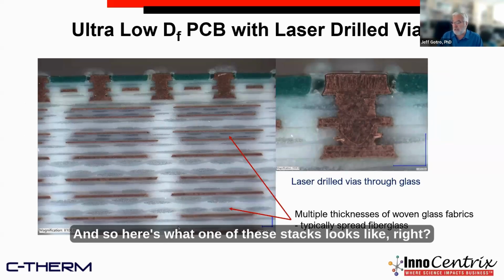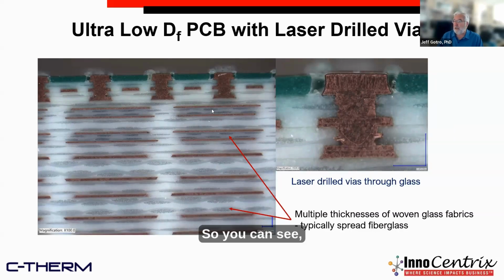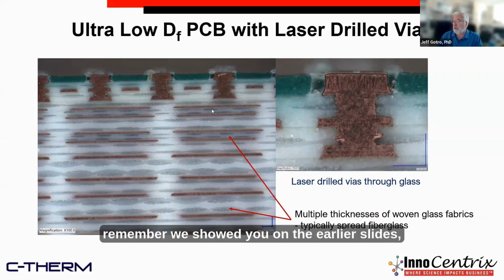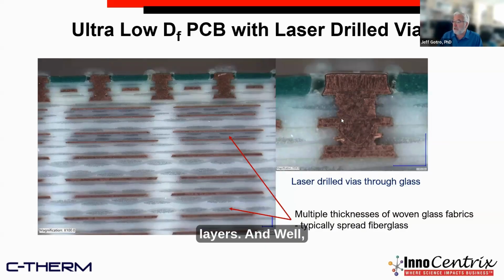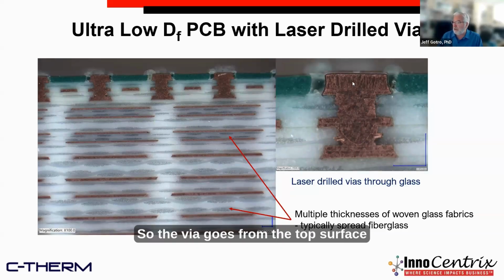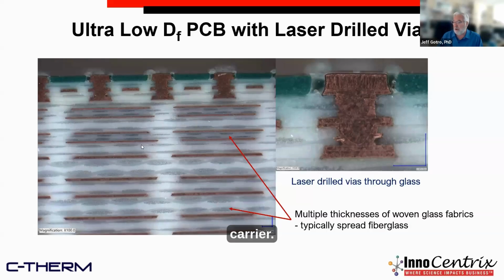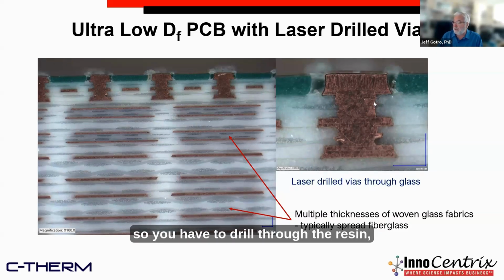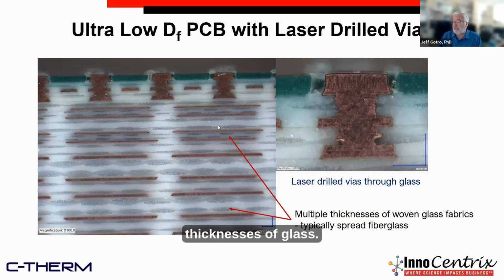And so here's what one of these stacks looks like, right? You can see, remember we showed you on the earlier slides, we have these stack-ups of the outer layers. Well, this is what we call here a through via. So the via goes from the top surface down to the inner surface inside of this carrier. And these are drilled with lasers. So you have to drill through the resin, you have to drill through the glass. And then there's multiple thicknesses of glass.